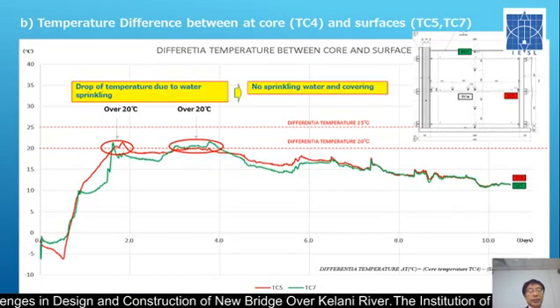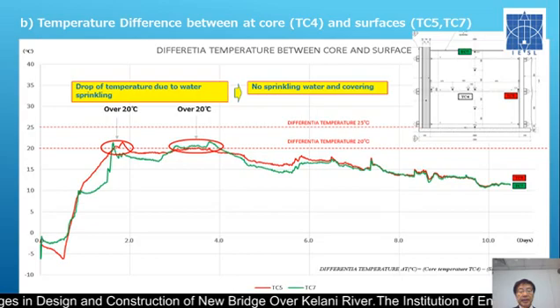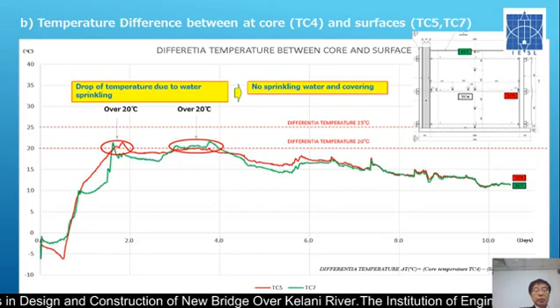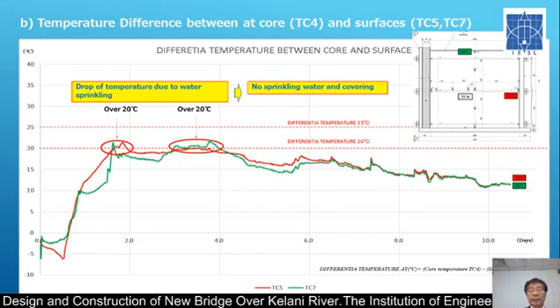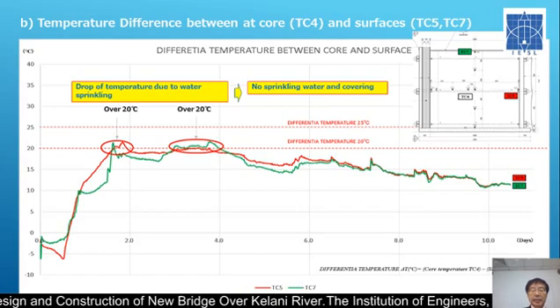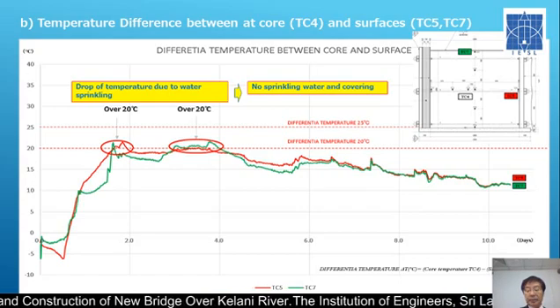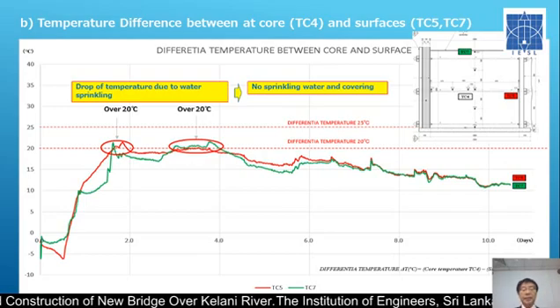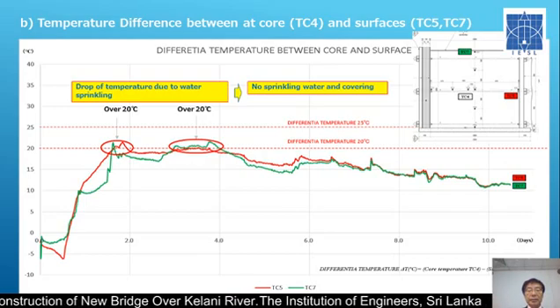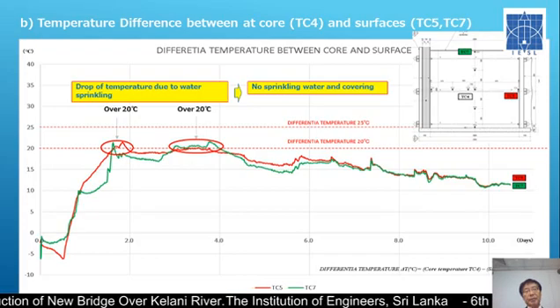But for the temperature difference in this specimen, there are 2 locations exceeding the requirement of 20 degrees. We observed that during the curing, the contractor sprayed cold water that makes the surface cold, so that the temperature difference becomes larger.